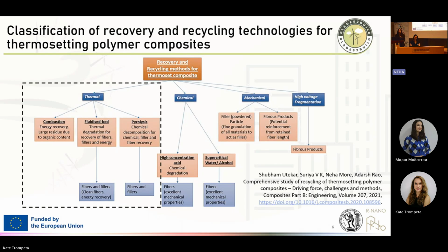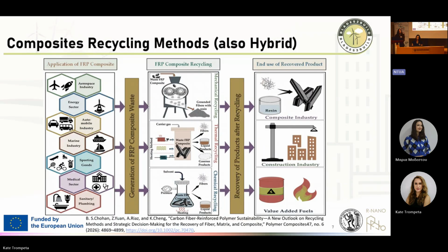In pyrolysis, we have a chemical decomposition for chemicals. We also have a recovery of the fillers and the fibers. In fluidized bed, we also retain the fibers and fillers, but we could also have energy recovery. And there is also combustion, where we have the main energy recovery, but it's not very eco-friendly and not very efficient. Here you may see that there are also hybrid technologies, hybrid composite recycling methods. For example, we could have some chemical, electrochemical techniques. We could also have a combination of the techniques in a series and sequential manner.